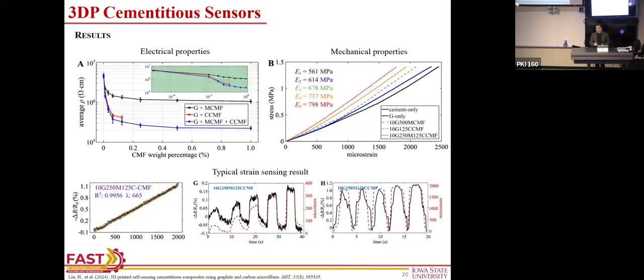The slope of that curve is the sensitivity. We call it gauge factor in sensing. Typical gauge factor for a sensor is 2. What we achieve here is 665. So quite improved, right? So we have a sensor that's very sensitive to strain. In the dynamic data we can see that we can follow the dynamic load. I mean, there's some discrepancies, but that's a good sensor.